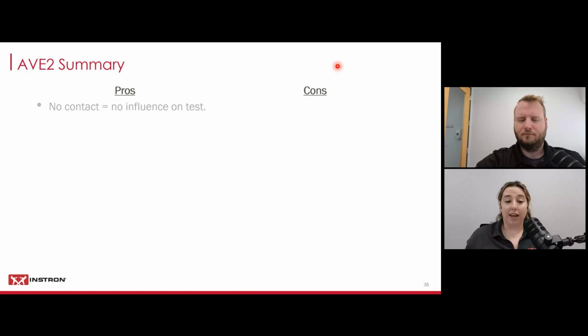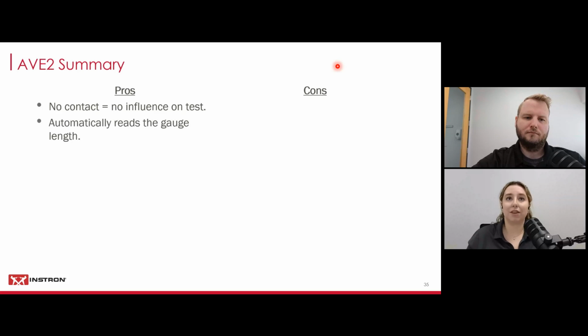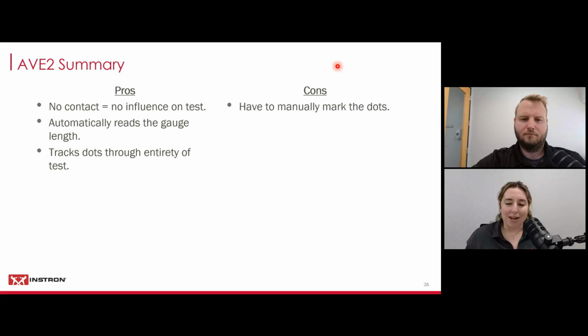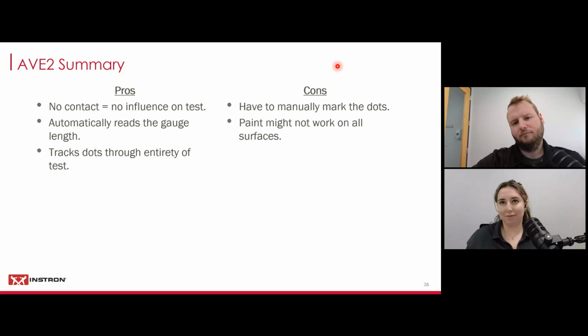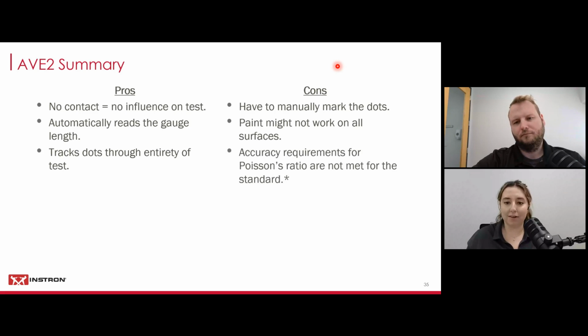So for the AVE pros, no contact means absolutely no influence on the test. We automatically read the gauge length. I could have done multiple gauges, I just did 50 millimeters. And then it was able to track the dots through the entirety of the test. Cons are that I did have to manually mark the dots, so that is a little bit of time. Your paint might not work on all of your surfaces. As I said, I was fine with the stuff that I had.